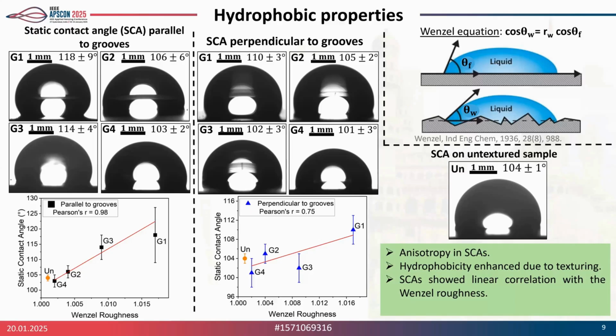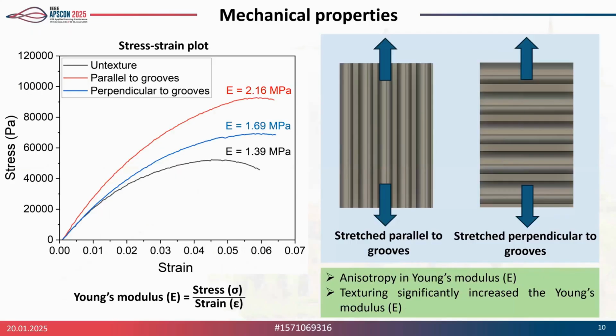The last thing you can see in these two plots is that the parameter I discussed earlier, the Wenzel roughness, showed a good linear correlation with the contact angle. The second property is the mechanical properties. We stretched the samples parallel to the grooves and perpendicular to the grooves, and there also you can see a clear anisotropy in the Young's modulus. If you compare with the untextured sample, the Young's modulus significantly increased because of the texture.